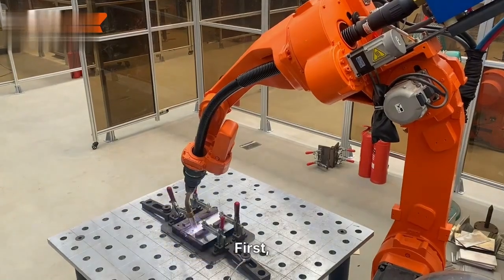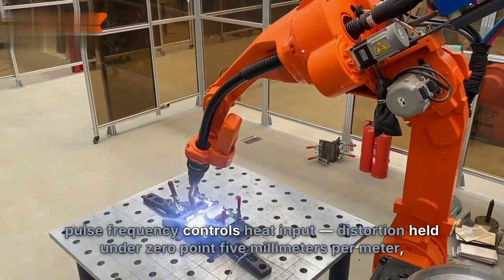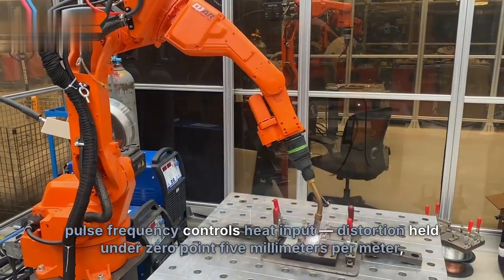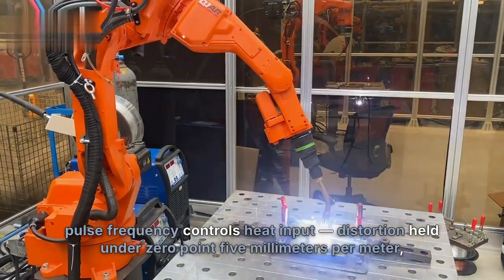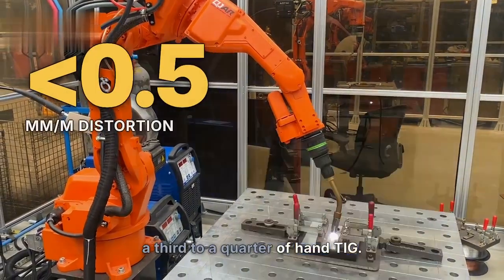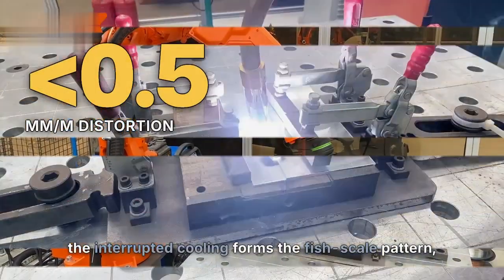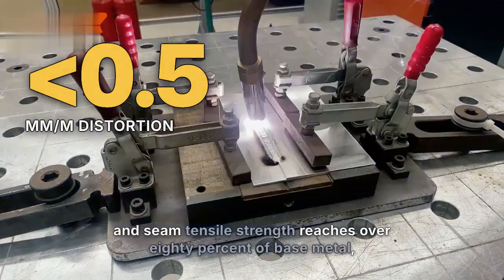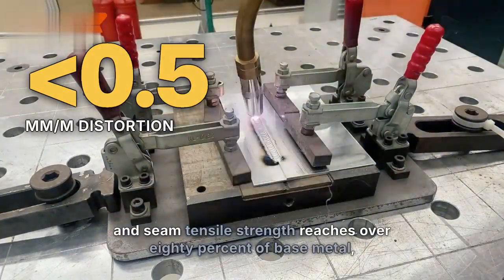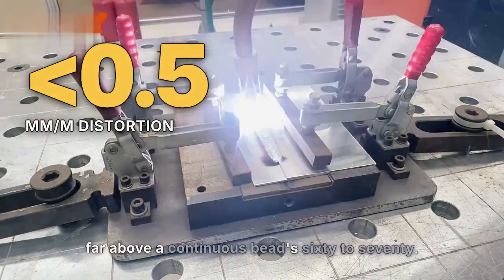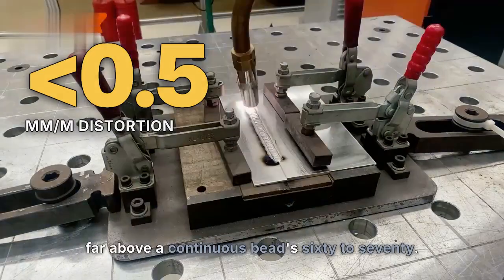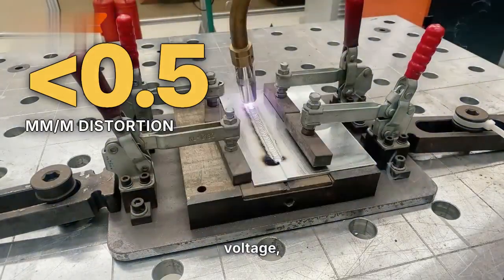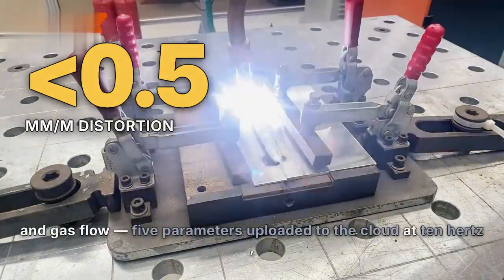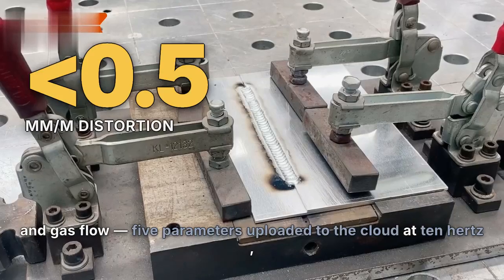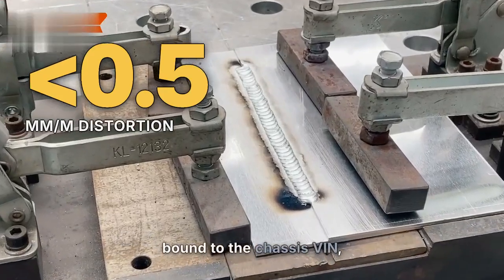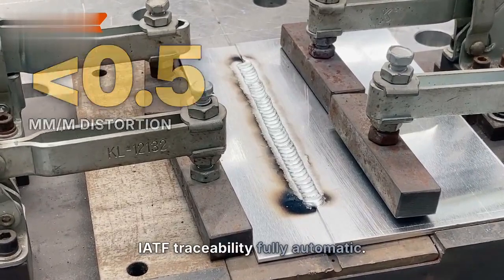3 cores. First, pulse frequency controls heat input. Distortion held under 0.5 mm per meter, a third to a quarter of hand TIG. Second, the interrupted cooling forms the fish scale pattern, and seam tensile strength reaches over 80% of base metal, far above a continuous bead's 60 to 70. Third, current, voltage, speed, wire feed, and gas flow, 5 parameters uploaded to the cloud at 10 Hz, bound to the chassis VIN, IATF traceability fully automatic.